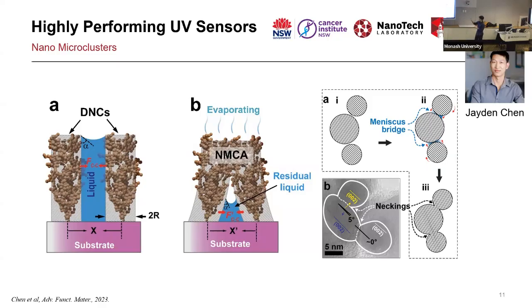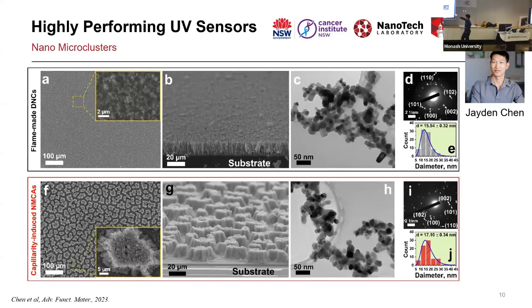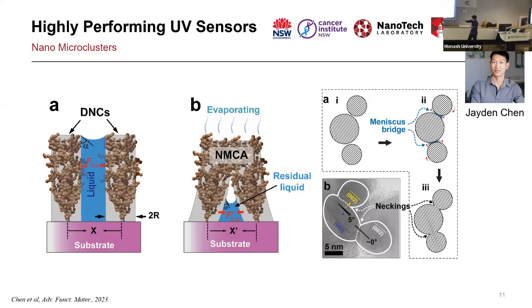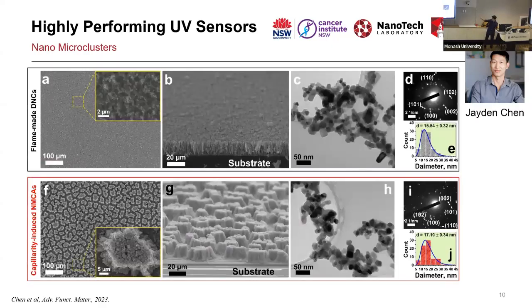We believe 2 things happen. In the macro scale, there are the clusters from the flame, and there is liquid between 2 clusters. The clusters I'm talking about are these ones here. There's a cone-shaped structure coming from the flame at a certain parameter. When we put a droplet, the liquid goes between all this structure. Now imagine the liquid is evaporating. Based on the capillary force, based on the Laplace pressure, at least this is what we think, it's pulling these 2 clusters, not only 2, let's say 5 or 10 of them, it really depends. It's pulling them together and creating that forest structure over there. At least this is what we think.